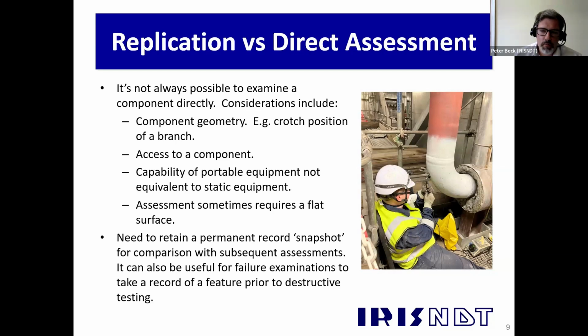The other thing is that if you were to try and use portable equipment, quite often it's not as user-friendly as static equipment. So from a microscope point of view, the field of view is generally much smaller. It's much more difficult to operate and focus, as I say, on a curved pipe, it's not easy to get a nice field of view. And again, that's the whole point of replicating, really, is to get that flat surface from what would otherwise be a curved surface. And we don't have any problems flattening out those kind of compound curves either.